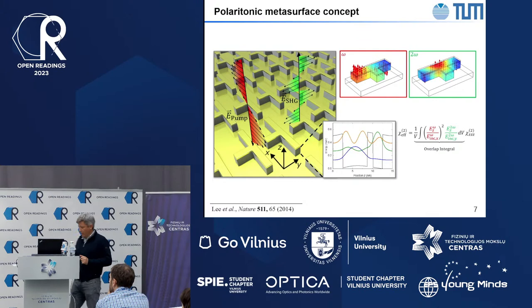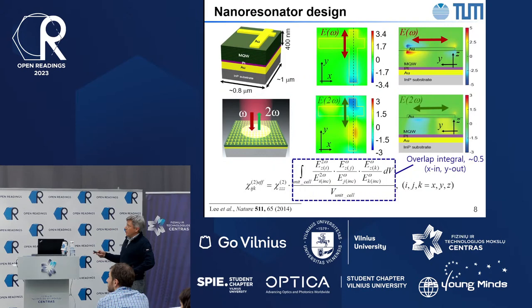So when we did the first demonstration in 2014, we had antennas that were designed like this. They were sitting on top of multi-quantum wells. And what is plotted is the strength of the electric field produced by excitation in this direction, about 100 nanometers below the top antenna.